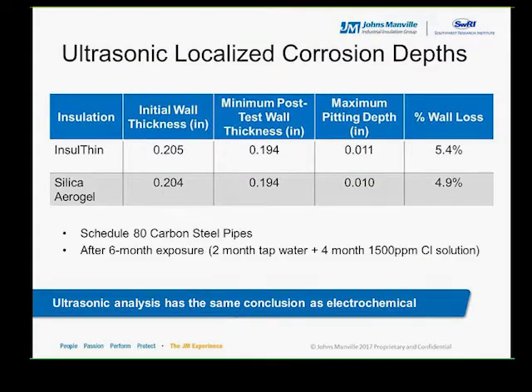Another way we looked at the samples was using the ultrasonic test method, and what we saw was the results depicted the same conclusions as the electrochemical methods. Shown here are the localized measurements of actual pipe thicknesses after a 6-month test. Keep in mind that the ultrasonic test method can only be taken after the assembly has been taken apart and the insulation blanket removed. So how this works is the ultrasonic test method measures different areas of the pipe section's remaining thickness after the corrosion test period.